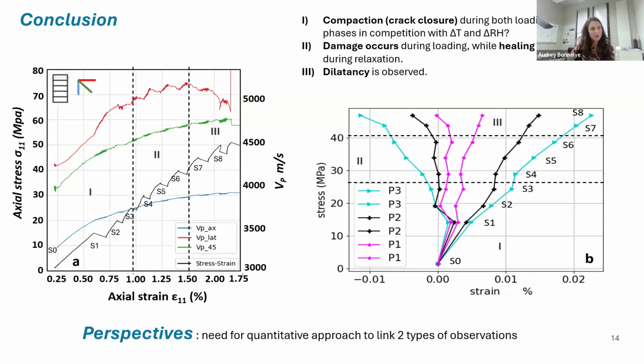But actually, this allows us to compare what is happening inside of the P-wave velocities with what we've been observing in the different phases of the material. So we do observe the compaction. All of the stress-strain curves that we've been presenting earlier are going toward compaction, and so all of our P-wave velocities are increasing. But then when we enter phase 2 of the deformation, when we start initiating the damage, which is equivalent to the C star value, we start to see a different evolution of the P-wave up to the moment when it decreases, which is reached prior to failure.